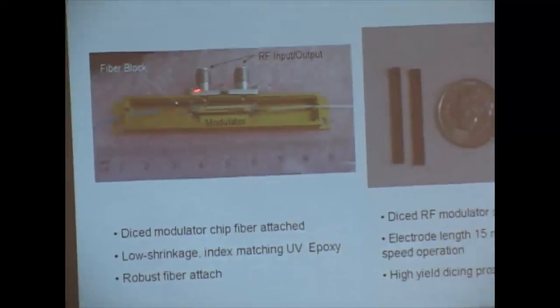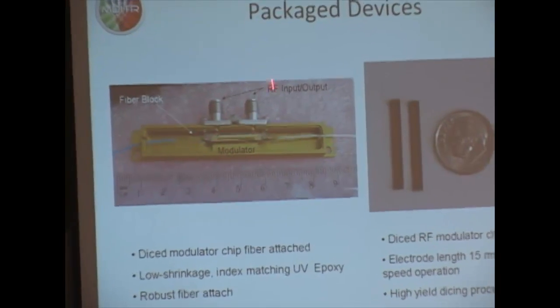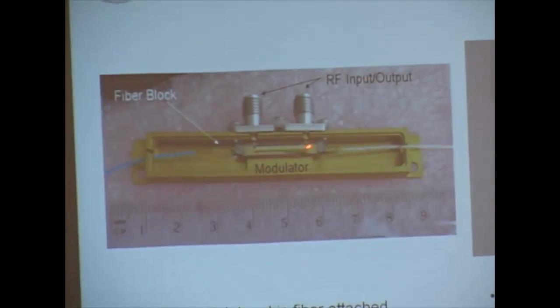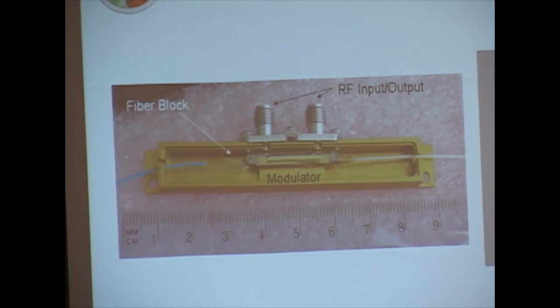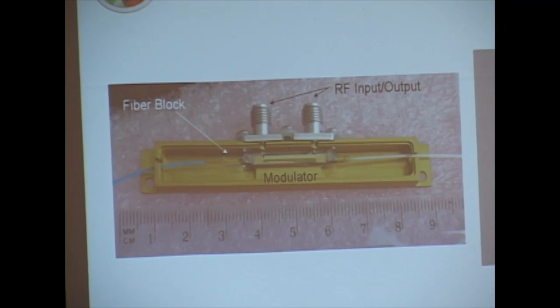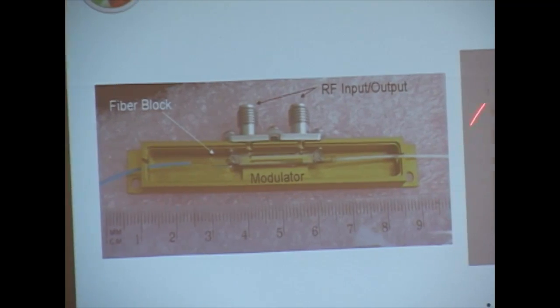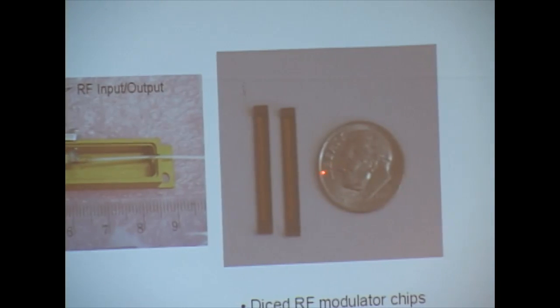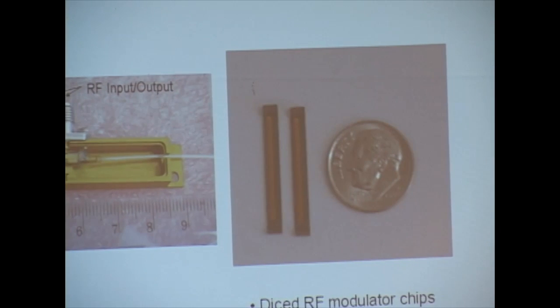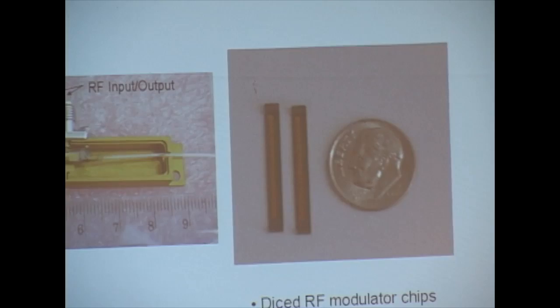So we use low shrinkage index matching UV epoxy for the modulator, and then these are the RF outputs. And then these little tiny pins have wire bonds to them. Basically, you can't see it at this level. And so these are our diced modulator chips. They're just a little bit longer than a dime, and they have 15 millimeters electrode length, and we get a high yield dicing process.